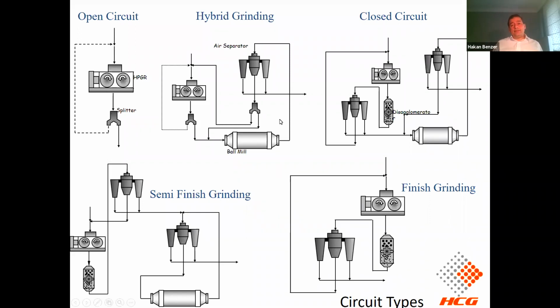Afterwards, the industry realized that the HPGRs produce significantly fine material, and if an appropriate classifier can be used, then the production rate or the advantage can be maximized. And this is the closed circuit application of the HPGR, running again with a ball mill circuit. Afterwards, again from the HPGR circuit, the fines generated can be used as a direct product. That's why 2 stages of classification are implemented, and this circuit type is known as semi-finish grinding. Right now, we have come to a point where the HPGRs can be used with a certain classifier to produce final cement, very fine material.